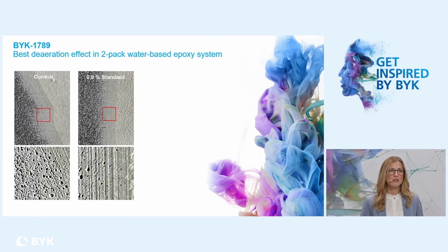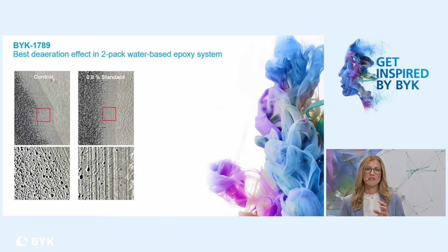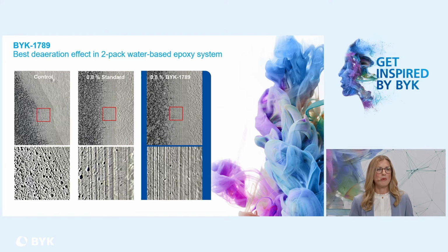The defoaming effect is also visible within the coating or at the interface of substrate and coating. In this test, we just spray applied by airless technology the coating on a test plate. And so the film thickness was about, let's say, 300 microns wet, more or less. And after some flash-off time and also some curing or drying time in the oven, the coating was removed again by a knife. By doing so, the protection layer on the substrate can be evaluated directly. And the sample with BYK-1789 hardly shows any entrapped air bubbles, and therefore BYK-1789 gives a perfect protection of the substrate.